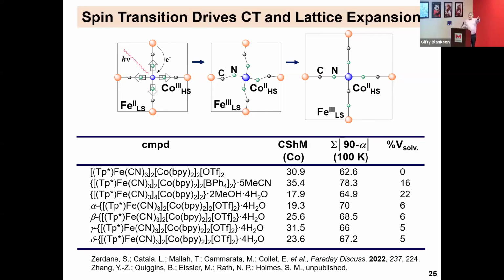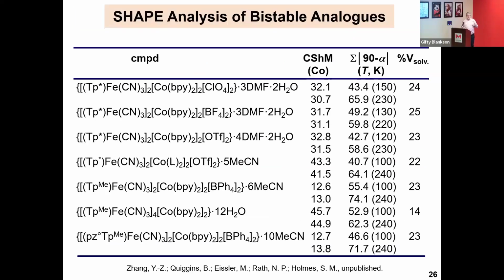None of these show electron transfer, although the ligands, anions, and the metal centers present should allow for it in theory. Now, if you compare that to other compounds where you do see electron transfer, both magnetically, optically, and spectroscopically, you can see that the volume of solvent around those molecules is ginormous. Again, if you don't have room to breathe, you don't. You have to expand and contract, and the solvent molecules have to be plastic enough to allow for that expansion.